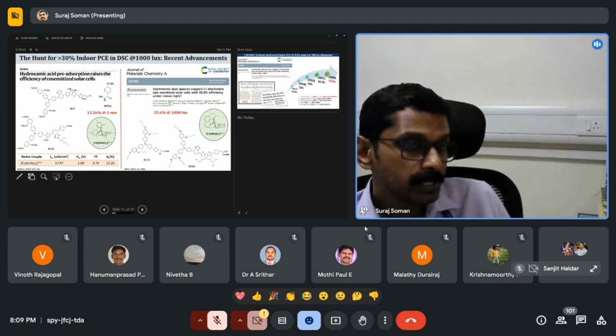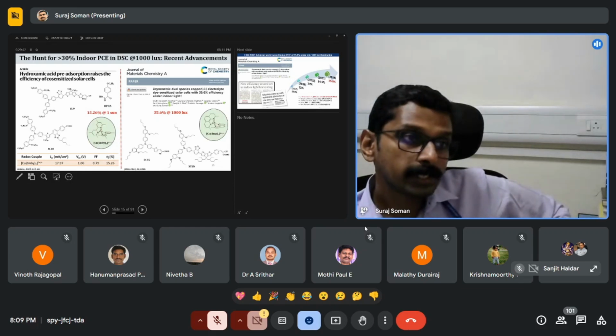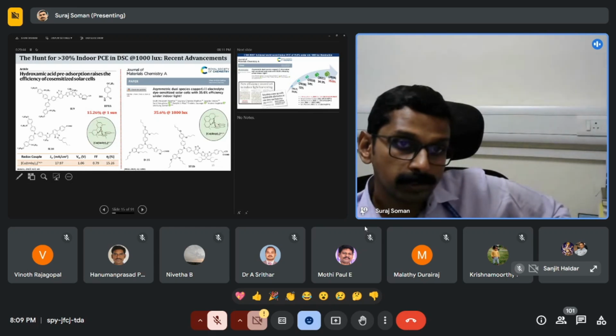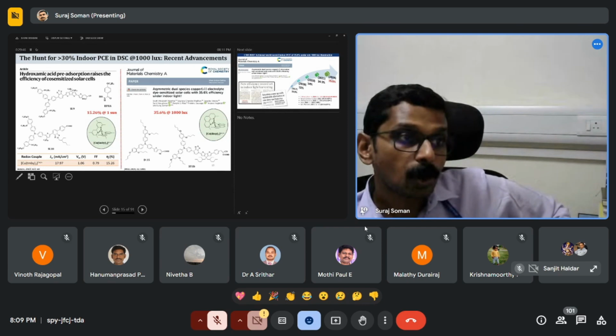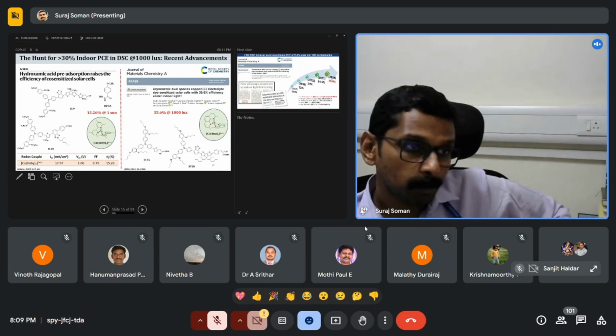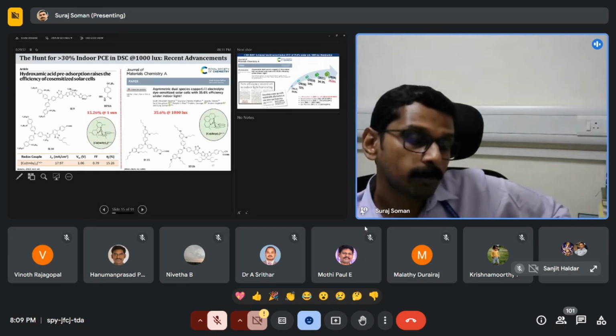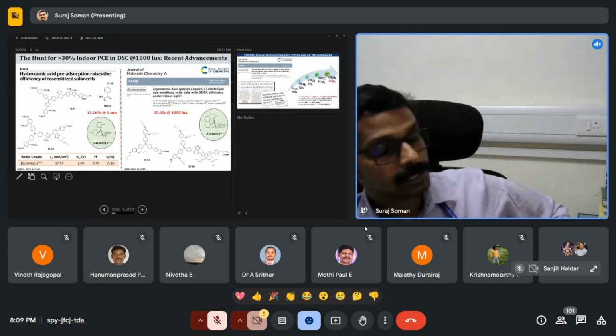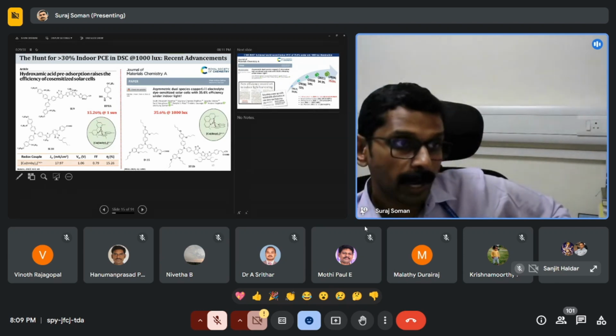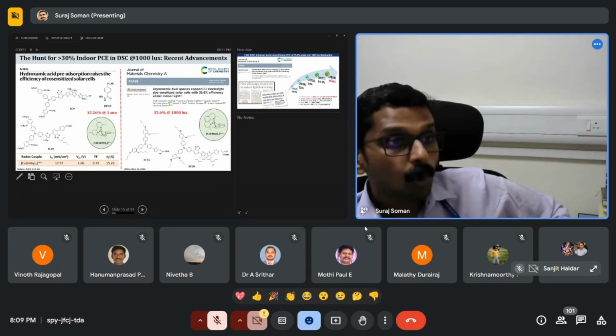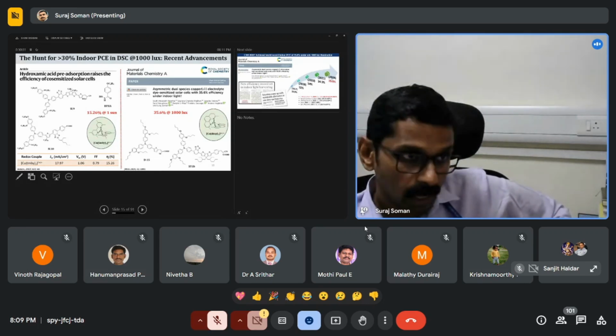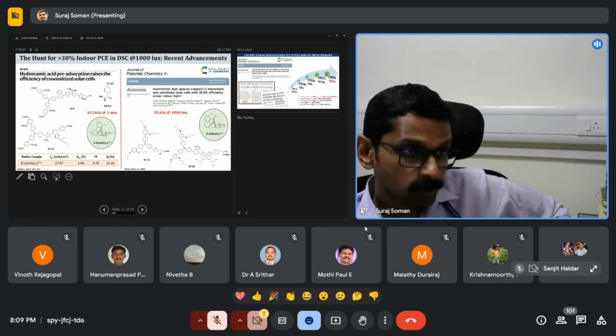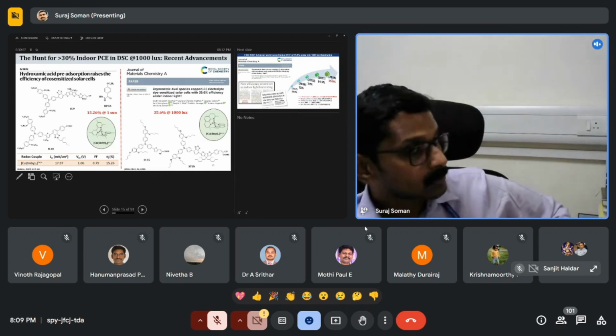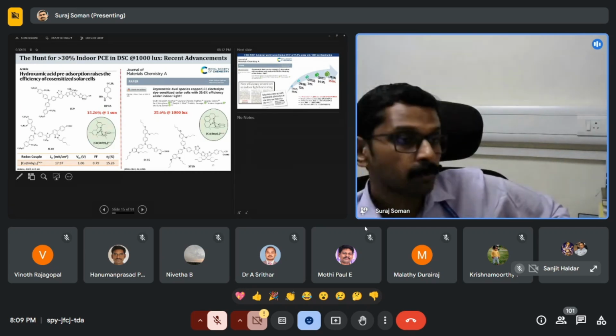Here in all these cases you can see that the researchers used organic dye. Instead of the ruthenium-based coordination metal complex sensitizers, which are the conventional sensitizers, here you can see a donor-pi-acceptor or a donor-acceptor-pi-acceptor kind of organic backbone system. These are scalable, more easy to synthesize and also highly stable molecules.